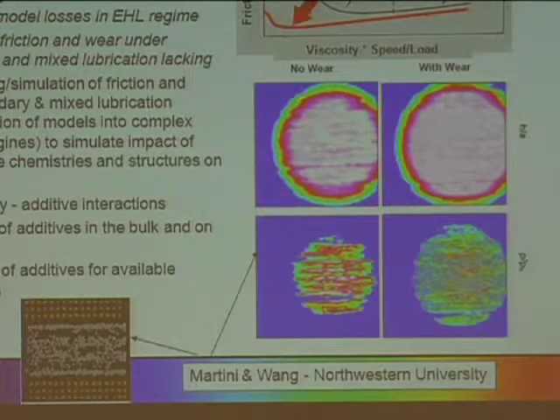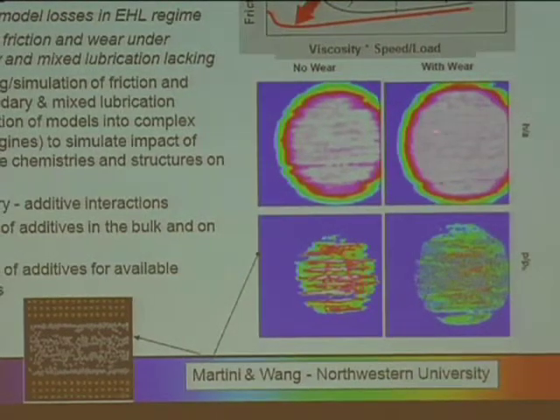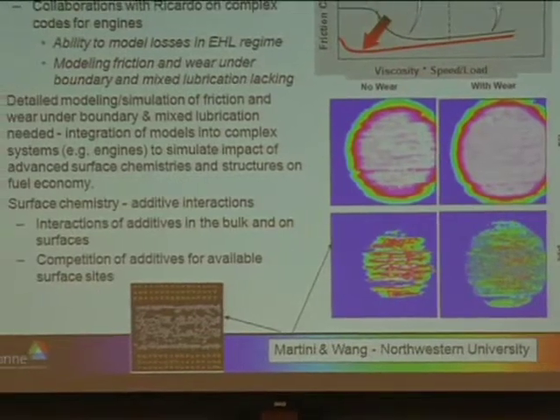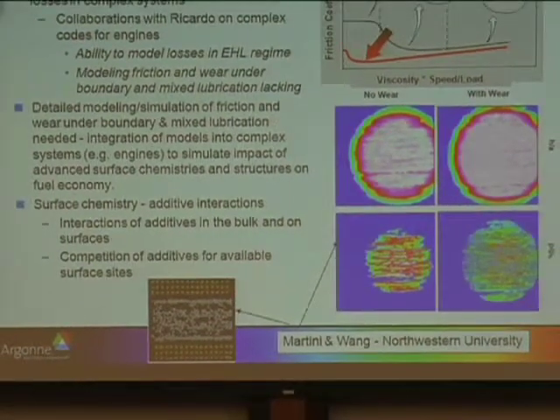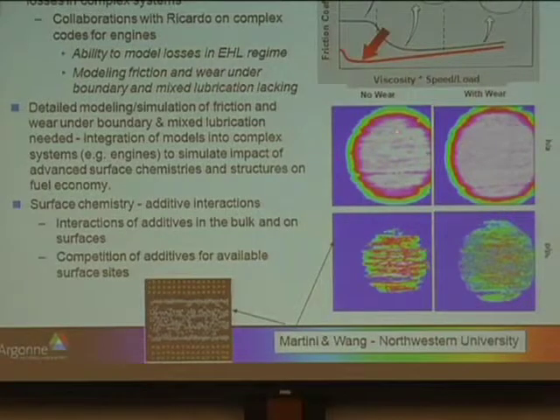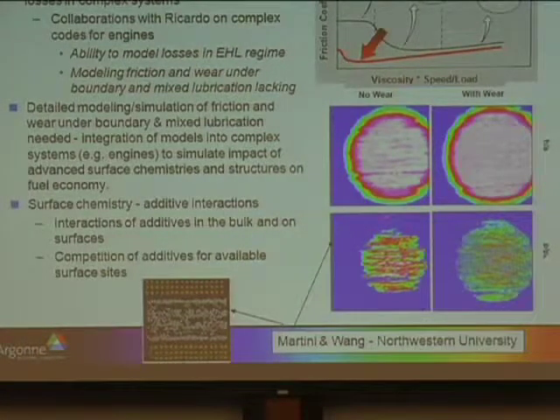They developed a model where they can essentially look at the effect of wear and how it changes the oil film thickness between sliding surfaces. They can actually take a representative surface finish with its roughness and so forth, put that into the model, and predict how that is going to wear as a function of time. And here you're looking at the effect during the start of the test where there's no wear, and then after these asperities have worn down, how the oil film thickness is changing, and also how the contact pressure is changing. Very important factor to include when you are trying to model the friction coefficient.